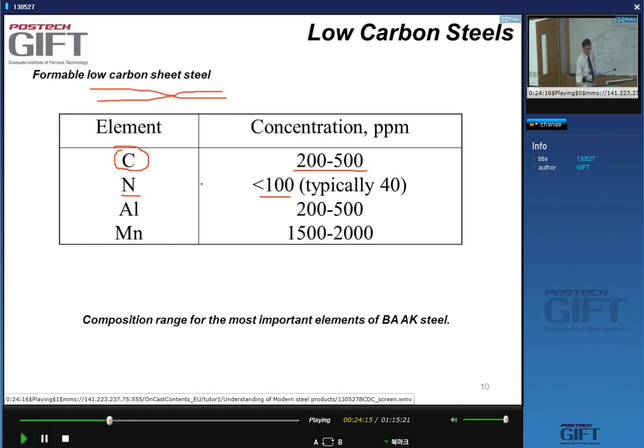But typically, if you use BOF material, the nitrogen content is 40 ppm. Yes? It's very difficult to get much lower. And you remember how this is done: very low levels of nitrogen and carbon are obtained by vacuum metallurgy. But for the low carbon steels, we don't do vacuum metallurgy, right? Okay. The other important point is the aluminum. The aluminum is 200 to 500 ppm. That's the range. Typically, if I want to be more specific, it's around 300 to 400 ppm. That's a narrower range. And then you have manganese at 1500 to 2000 ppm. That corresponds to 0.15 to 0.2% of manganese.